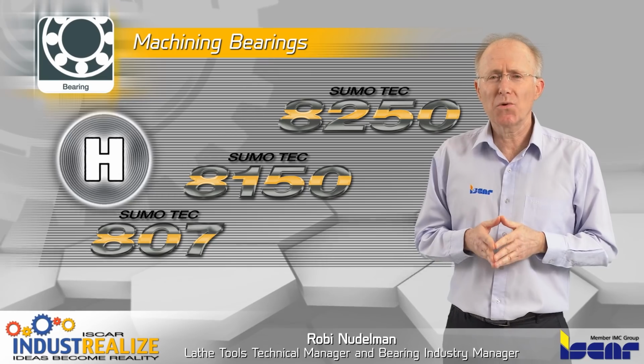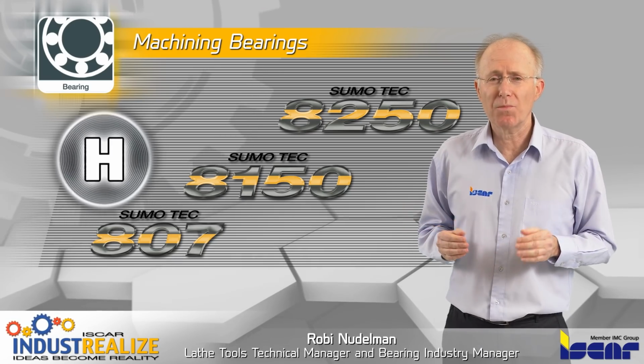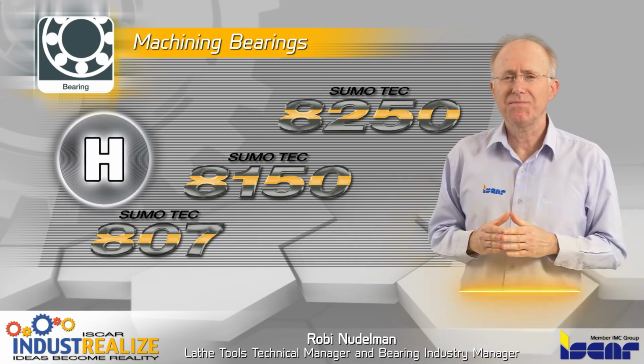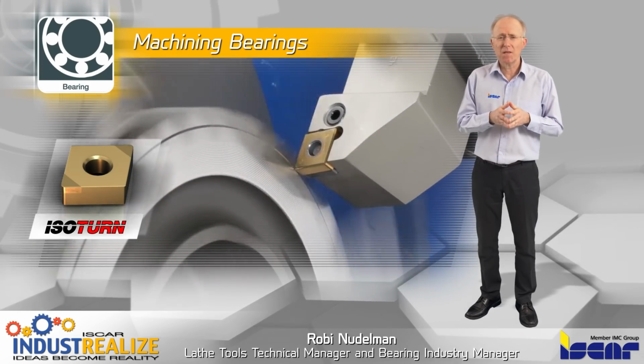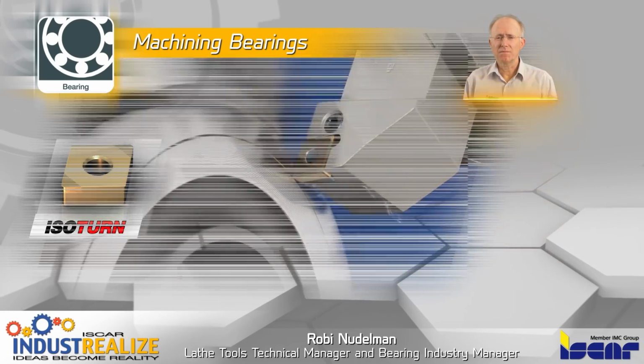The CVD coated grade IC8250 is recommended for rough turning operations and IC8150 for finishing operations. Another finishing recommended grade with PVD coating is the IC807. For turning of hardened rings up to 62 Rockwell C, ISCAR offers ceramic and CBN inserts for high-speed machining. By using these inserts, grinding operations can be eliminated.